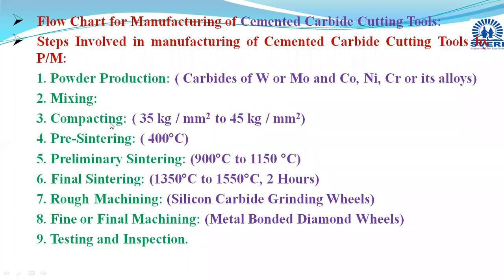Then that uniform mixture obtained will be given to the compacting stage, and in this compacting stage we are doing three steps: filling, pressing and ejection. The compacting pressure used is in the range of 35 to 45 kg per mm square. Within this range, sufficient compacting is done, and by raising the lower punch or plunger, that green compact is obtained, and it is given to the sintering. Now, sintering is conducted in three different ways.